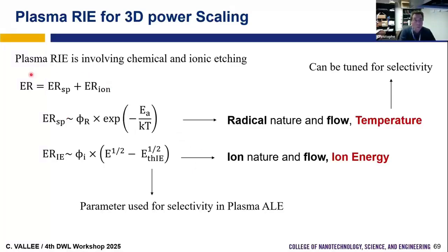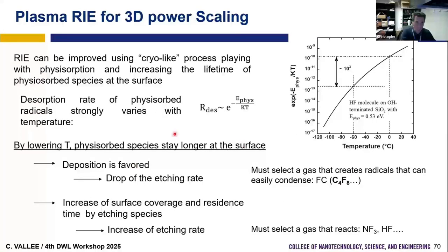So if I take the two components we have when we do the etching, we have radical flowing, so we have a spontaneous etching, and the spontaneous etching is controlled by the radical flux and the temperature, so radical and temperature. And we have the reactive ion etching, where it's more controlled with the ion flux and the ion energy. And to modulate the ion energy, the threshold is what we use, for example, for selectivity in plasma ALE. If we have a spontaneous etching, we can say that we can play with temperature to try to tune for selectivity. So if we have isotropic etching and more, maybe we have to play more with the temperature to modify the selectivity.